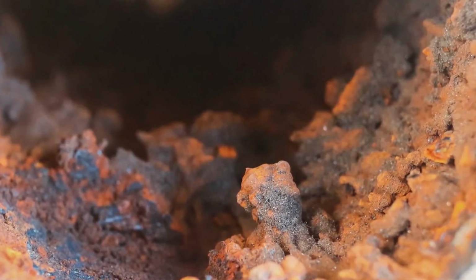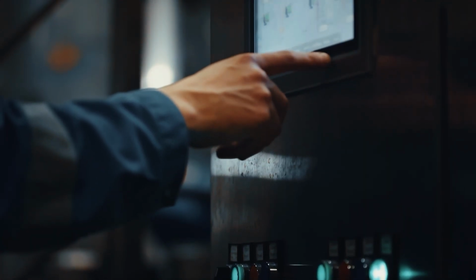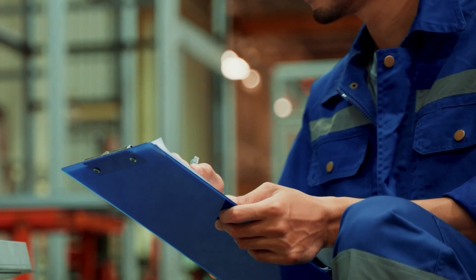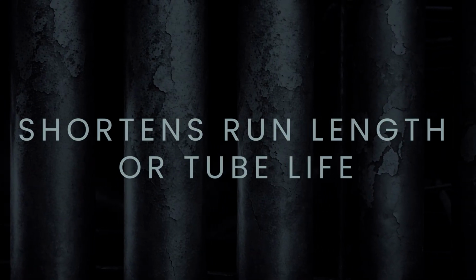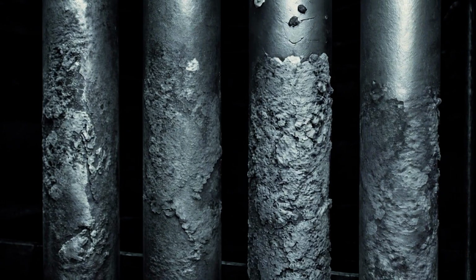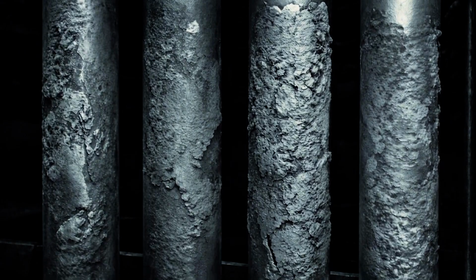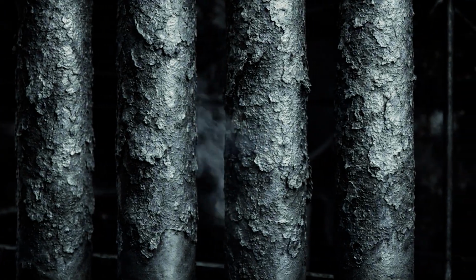Scale buildup negatively impacts your bridge wall temperature. It contributes to the operational bottleneck that many of us see after just a few years of service. Certainly, it reduces your reliability, and in severe cases will actually shorten your run length or your tube life. Now, in the higher chrome alloys, such as 5 and 9% chromium, those behave differently. The scale builds up differently, meaning it's thicker, it's more adherent, it's porous, but this scale does not flake off easily. Instead, it acts as an insulating barrier.